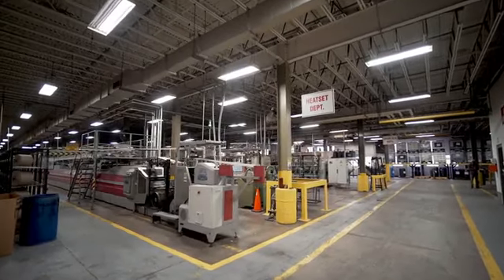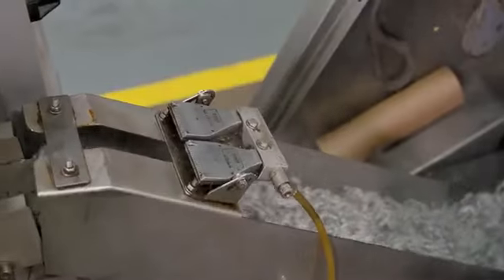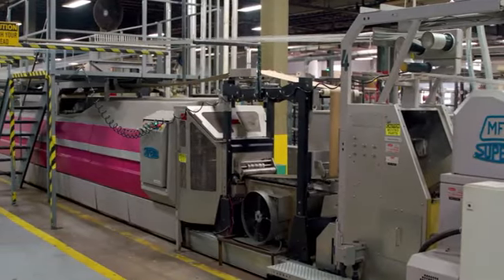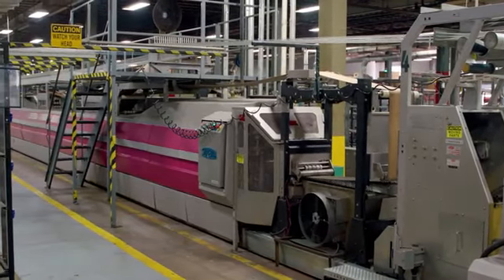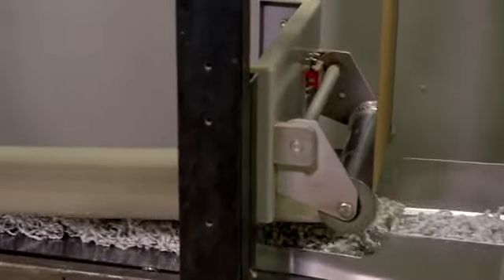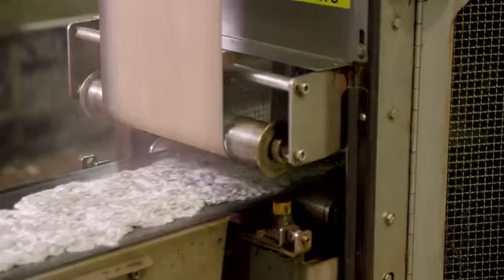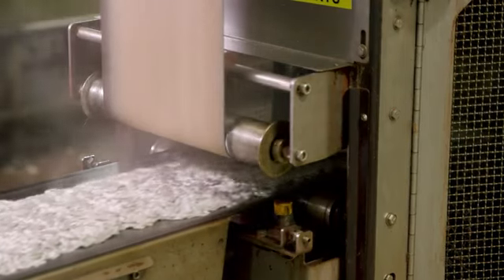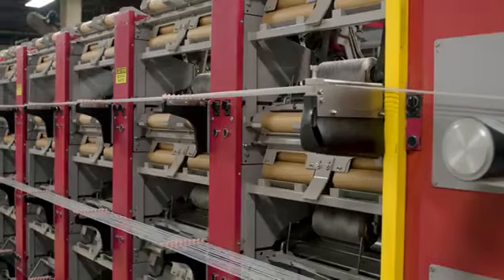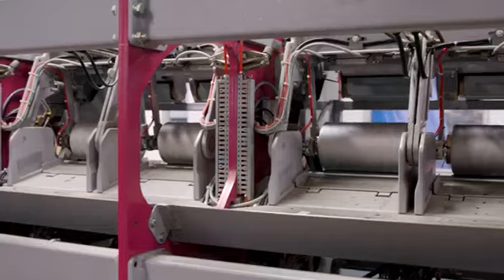The heat set process takes place directly after twisting. At this point, the yarn runs through a closed, steam-pressurized tunnel to prevent any unraveling of the twist. This process also makes the yarn durable, helps to hold its form, and increases the resiliency of the yarn. At the end of the heat set process, the yarn is then rewound onto cones and is ready to go to the looms.